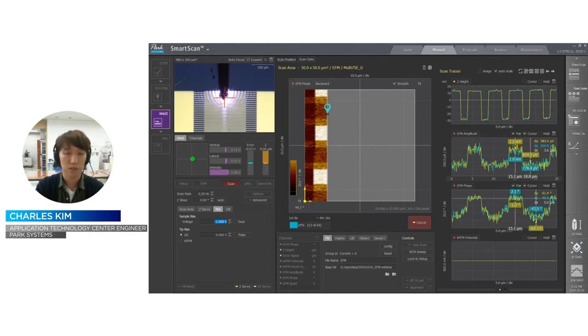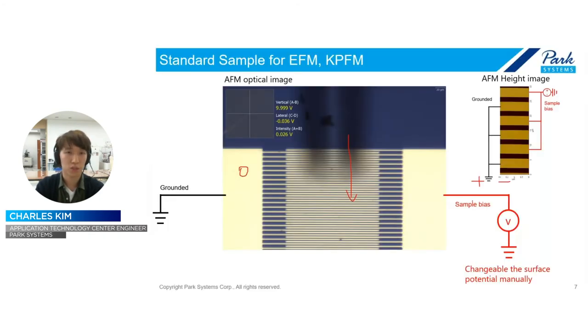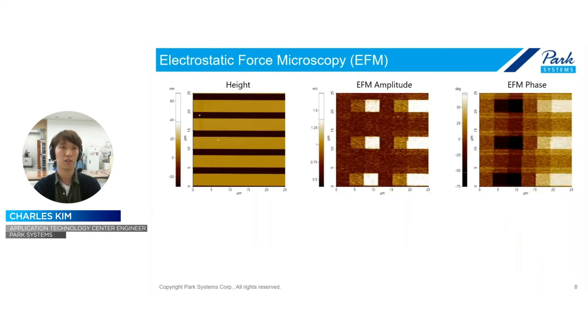So if I measure the surface like this with different sample biases, actually I already measured the image because of the time limitation of today's talk. I already finished the measurement like this. Please see this slide. The EFM amplitude I mentioned before represents the magnitude of the electrostatic force. And the phase is the polarity of the electrostatic force.